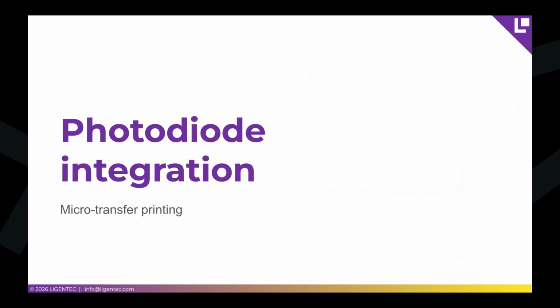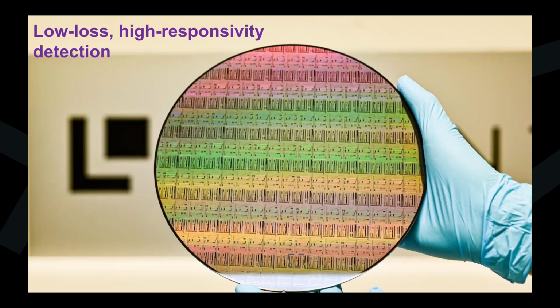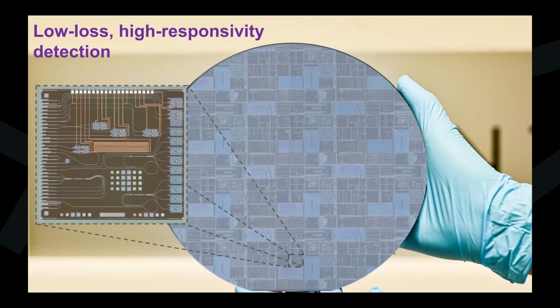The high-speed modulator can thus be used in integration schemes where we want to have a transmitter device and modulate that at high speeds up to 120 gigahertz. But you also want to have photodetector integration on the chip itself, and here we address the on-chip photodetector integration with an approach of microtransfer printing, and that is also a wafer level approach to get III-V components on the low loss silicon nitride chip itself.